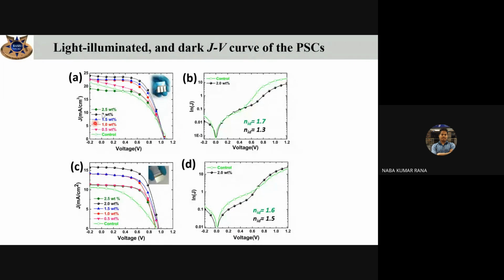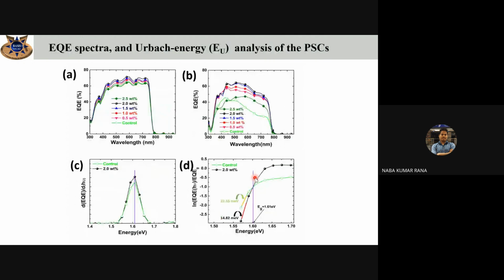We found that approximately 2 weight% of this small concentration of Al2O3 increases the device efficiency, and the maximum efficiency is 14% in small area. In large area, we have achieved approximately 9% efficiency, which is very difficult. As I already said, after introduction of this nanoparticle, the diode behavior increases and the ideality factor decreases, both in small and large area devices.